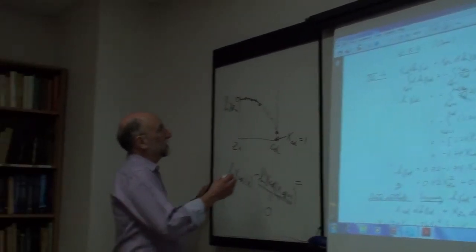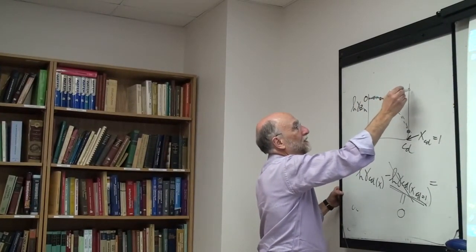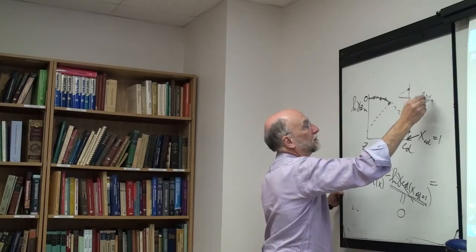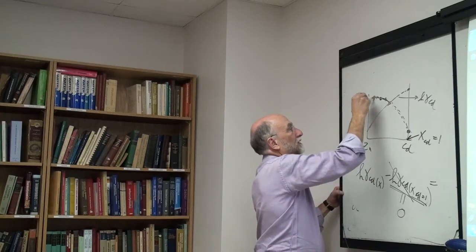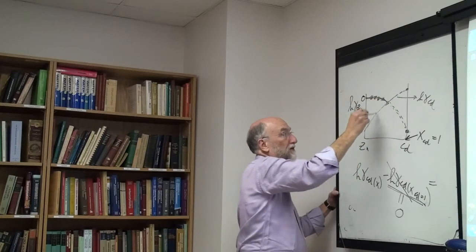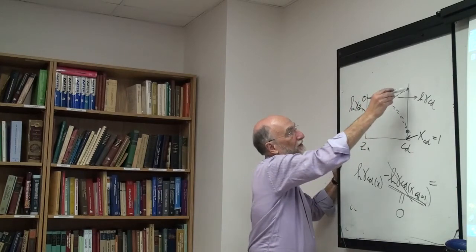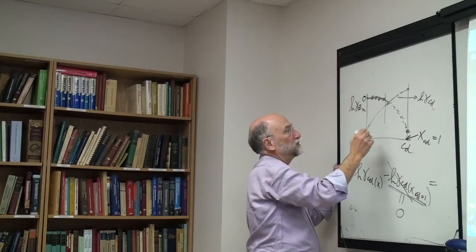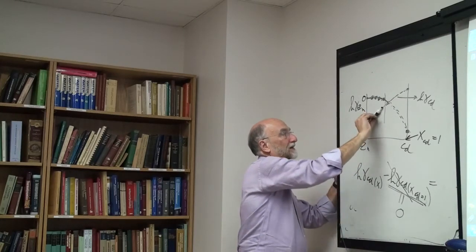Okay, so what you're going to get is log gamma cadmium. Let's just look at the same thing then. The log gamma cadmium looks like that. You've taken your log gamma zinc and integrated it from this point to give you your calculated curve for log gamma cadmium. If your experimental data really go over to that point, then everything's fine and you can calculate the thing. But if your experimental data only go over to this point, then the slope and everything here is correct, but you could be off by a constant.